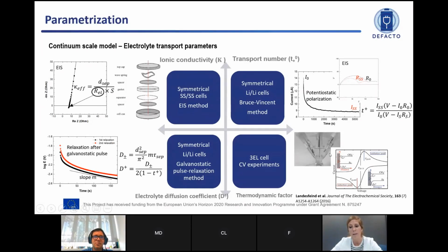And for the thermodynamic factor, we need to assemble a three-electrode configuration and perform the CV experiments. So basically, this requires a huge amount of experiments. It's quite tedious and time consuming. So we aim here to reduce the number of setups and optimize the testing methods, and this will be done by the model-based parametrization, as I was mentioning.